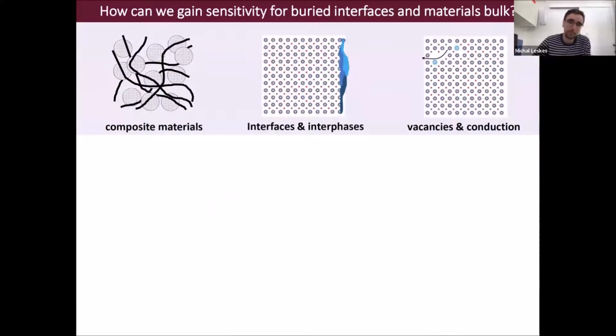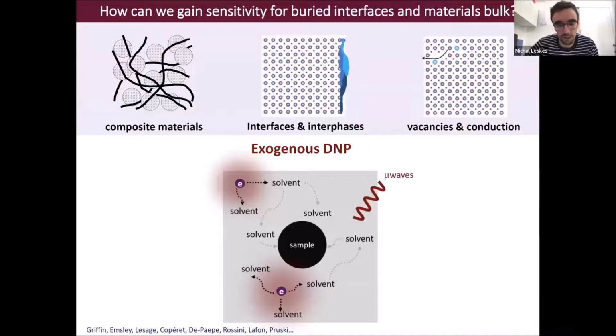Most groups that work on inorganic materials and apply DNP on them use the following approach. They soak their sample of interest in the so-called DNP juice, which contains some organic radicals, which then upon microwave irradiation can transfer the polarization of these unpaired electrons to the proton nuclei nearby, and then through proton-proton spin diffusion, the hyperpolarization is transferred to the surface of the sample. This approach, however, suffers from a limitation, which is that most of the enhancement will be limited to the first surface layers. And if we are interested in deeper layers beyond the first of the surface, or even if we're interested in bulk properties of the material, this type of DNP approach will not bring us much forward.